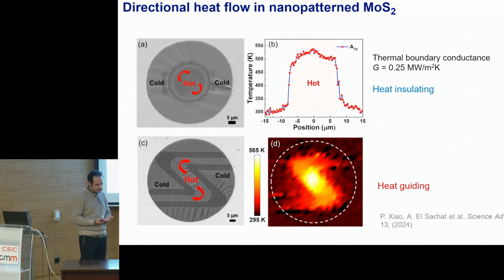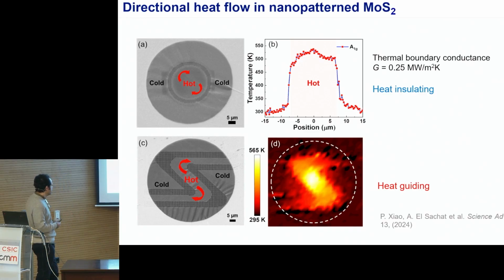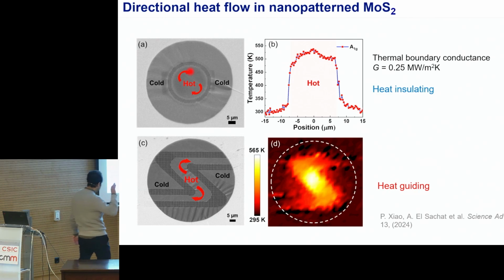But the most interesting thing in this study is that we can really control the heat flux in our suspended membranes. Here you see some specific patterns that we did on top of the molybdenum disulfide flakes. This insulating ring, where we create two different areas around the insulating ring, and in the middle is the hot area. Here you see the temperature profile. So I will not use probably this because this is a problem. Okay. And you see that we can create different areas with different temperature on top of the suspended material.